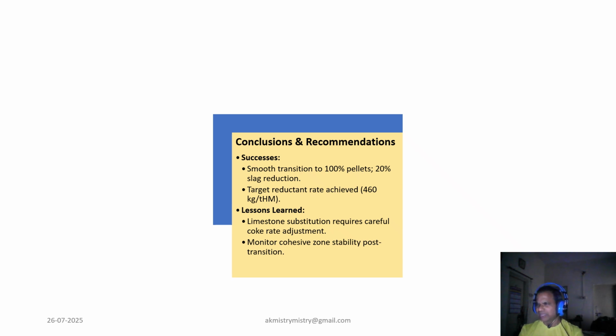So in conclusion, it can be said that the transition to 100% pellet was smooth and strategically successful, which is evident from the gradual top temperature and utilization trends. This also gives us feedback that the transition was very stable, with a 20% drop in slag volume and a reductant rate of 460 kg per ton hot metal as the final outcome. However, limestone substitution must be carefully balanced to avoid unintended impact on coke rate. Post transition, it's crucial to keep an eye on cohesive zone stability to preserve furnace health.